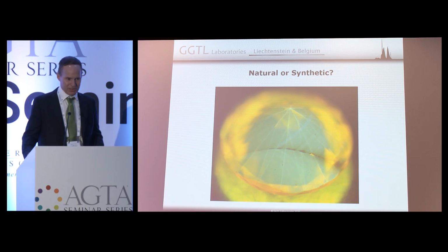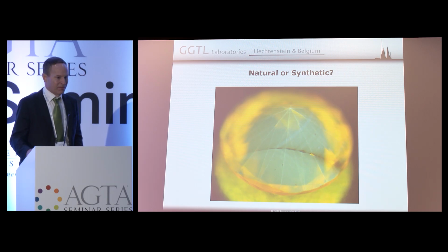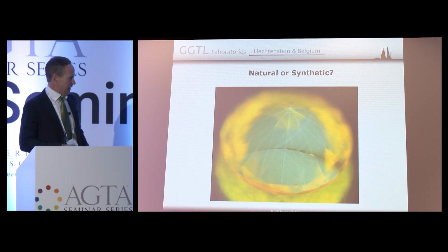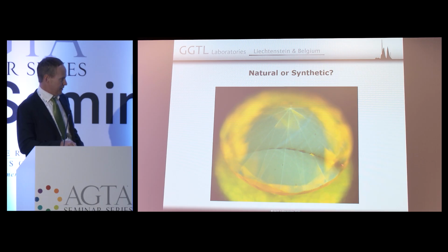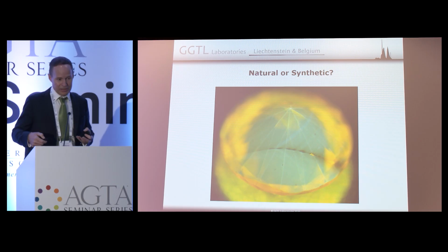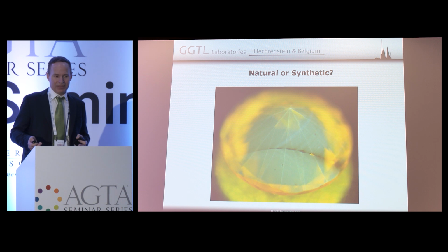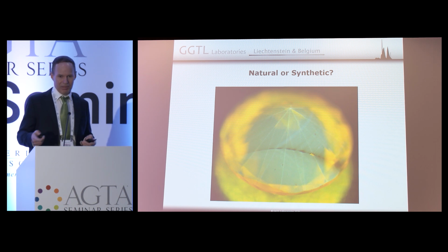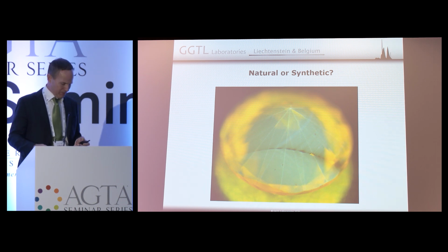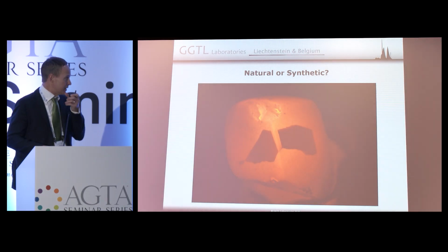This one, natural or synthetic? This is indeed a synthetic. So this is a different type of synthetic. Here I'm not sure if this was actually a twin, it's possible. And you see these interesting lines. So synthetics may appear rather different to what you see published everywhere. Those typical sectors sometimes look rather distinct, different. This one?